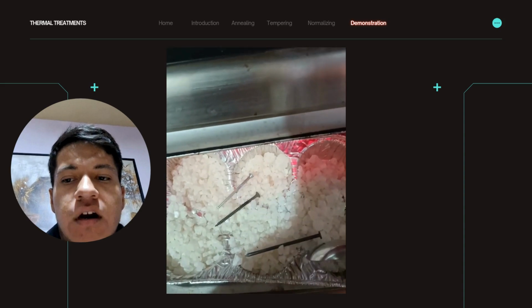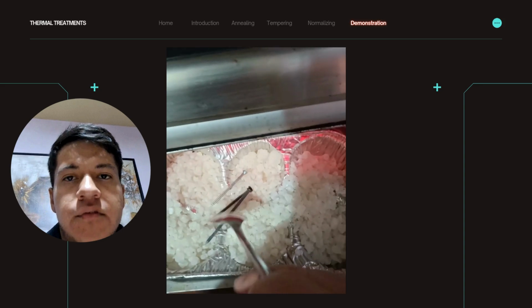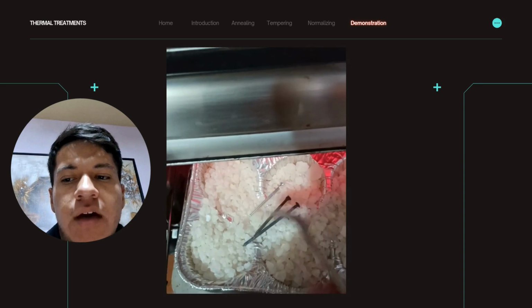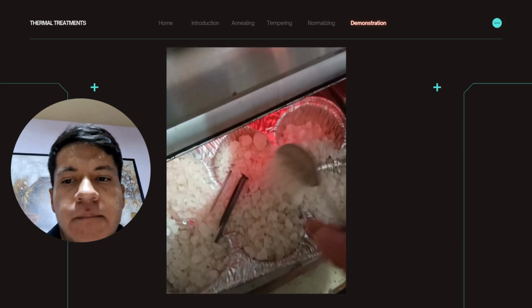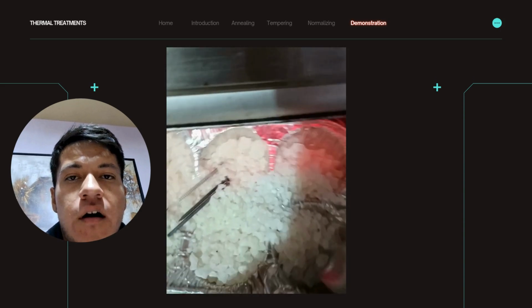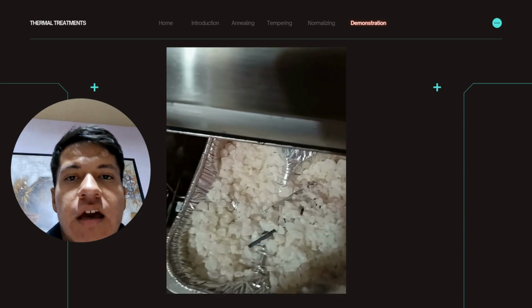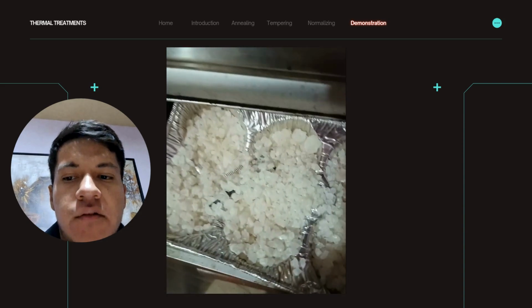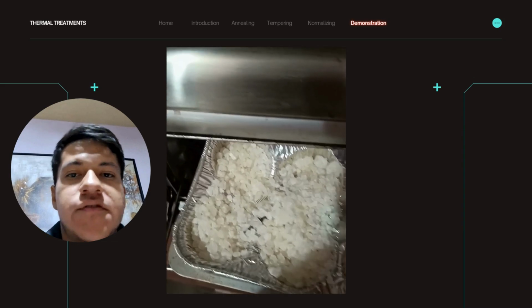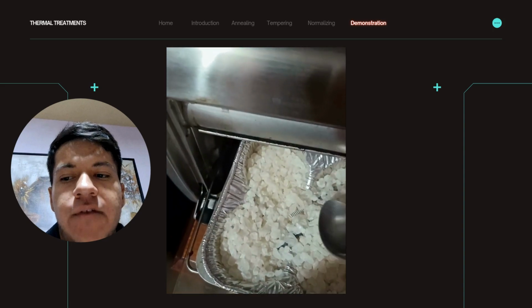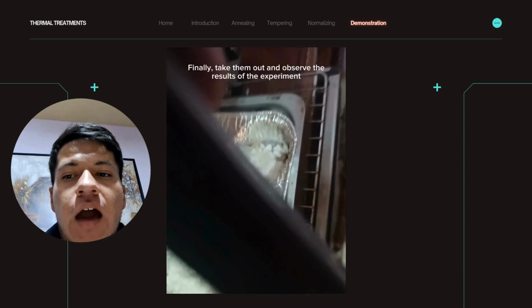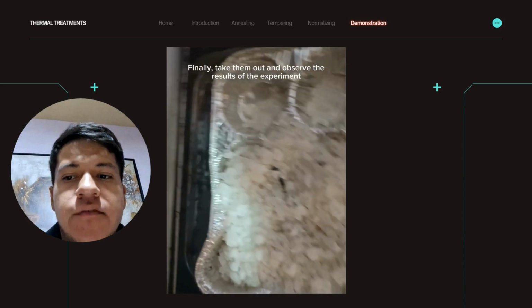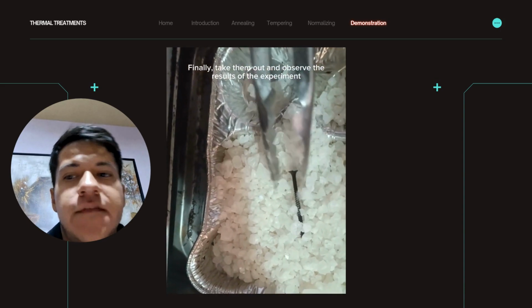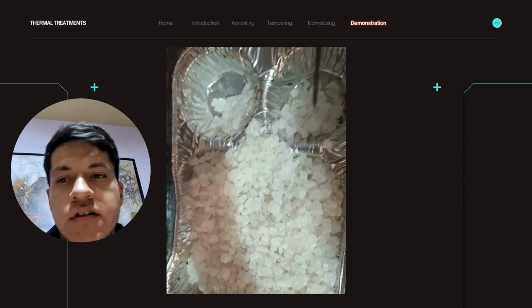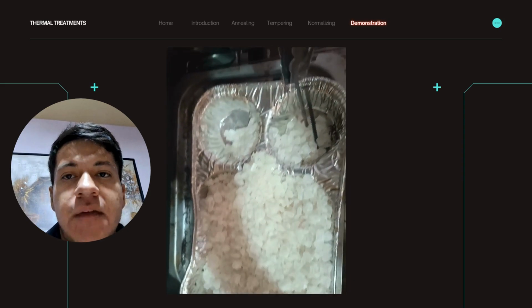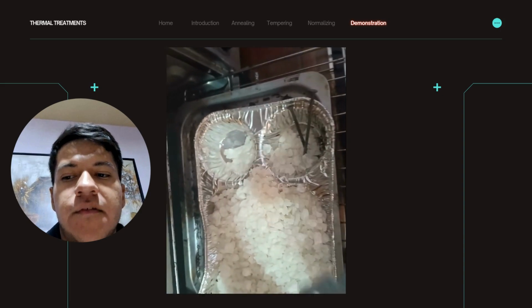This reduces hardness and makes the metal more ductile, but we observed a few interesting changes. First, all the pieces looked less shiny and more gray, especially the drywall screw and the nail. Their surfaces felt rougher and drier than before. However, when we tried to bend or test the flexibility of the pieces, there was no noticeable difference. They remained just as stiff as they were before the heat treatment.